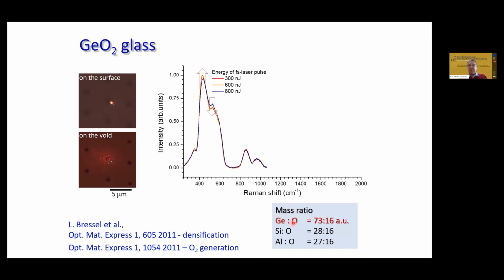So germanium and oxygen has a bigger mass ratio if you compare aluminum and oxygen in sapphire. So here it's not a complicated experiment using synchrotrons. This is simply fabricating voids in glass and looking for Raman scattering. You can recognize the modification of glass. It's all understandable from glass science.